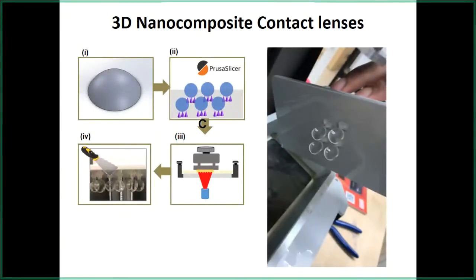But eventually we found out that during the process, at all of these stages, the samples were getting contaminated by some acid. That acid was not on the surface, it was in the gel itself during the curing process, coming from the beakers or containers. So yes, this is a very good point. During the fabrication, the containers, the beakers, everything that you're preparing these liquids in, everything should be clean.